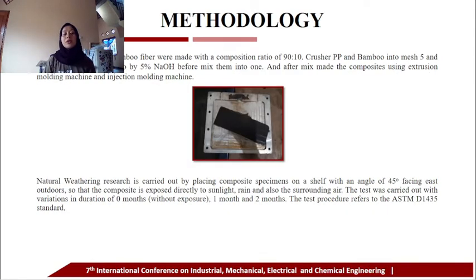Composites of recycled polypropylene bamboo were made with a composition ratio of 90:10. First, crush polypropylene and bamboo into mesh 5 and then treat the crushed bamboo with 5% sodium hydroxide before mixing them into one. And after mixing them, melt the composites using an extrusion molding and injection molding machine.